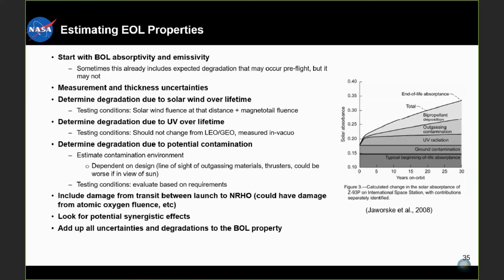So in addition to the environmental effects like solar wind and UV, you also have the degradation from contamination that you'll need to take into account. And this can be difficult to quantify just because not only do you need to understand which contaminants you have, you also need to understand where your surface is relative to those contaminants. So that's going to be really dependent on your design. So you'll need to think about the line of sight between your surface and your outgassing materials, or thrusters, or if you're in the view of the sun, that could potentially be worse due to the synergistic effects that we mentioned earlier. So you'll have to develop some testing conditions based on your design and what you know about contaminants that are involved in your spacecraft, and then you'll evaluate the results of that based on your requirements. So you'll be able to come up with a delta that you expect for your contamination to add basically to the degradation you expect for your end-of-life properties.